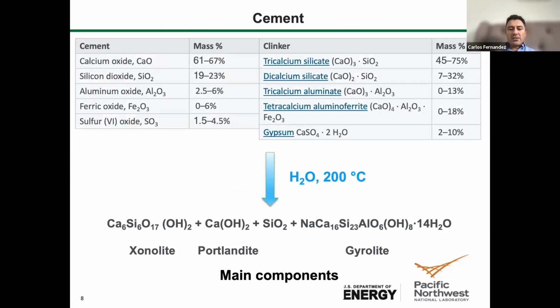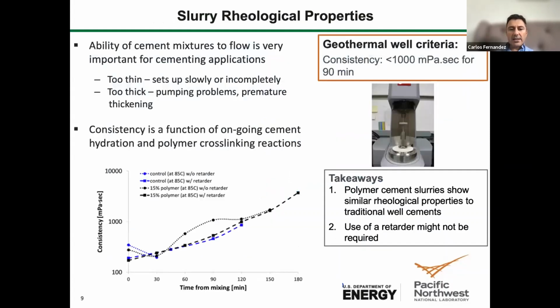Very quickly, at 200 Celsius, I think everybody knows, for cement with silica flour, the main components are xonotlite, portlandite, and scawtite, with some of the quartz in excess. Calcium hydroxide, obviously portlandite, continues reacting with the pozzolanic material to form calcium silicates. We all know that, and we haven't seen that change in the presence of the polymer, except in a couple of formulations.